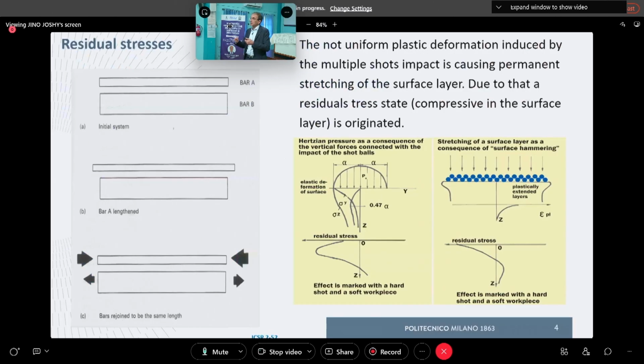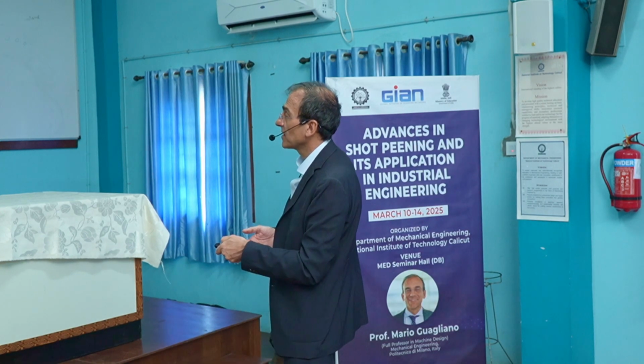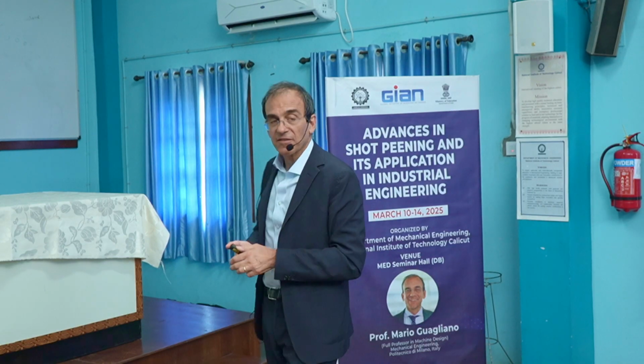The Hertz contact has the stretching effect due to the multiple indentation of the shot flow. In terms of Hertz, we have this residual stress distribution with a compressive residual stress on the surface, and the peak under the surface, at a depth that is related to the applied load. If we refer to the effect of stretching, the trend is this, with a maximum at the free surface and then rapidly decreasing and becoming positive at a certain depth. And the same happens for the Hertz distribution.